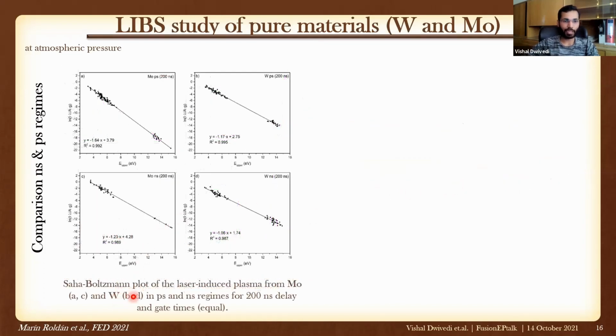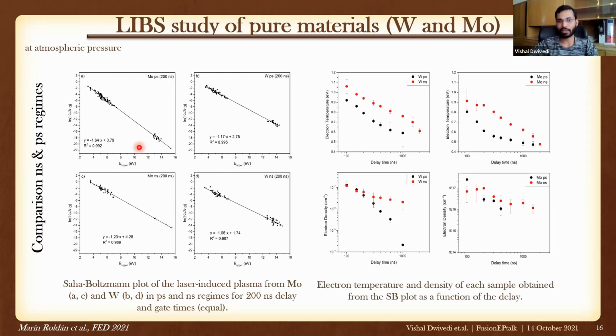Also from the same paper, these are the Saha-Boltzmann plots. From here we can evaluate the plasma temperature. These are for picosecond tungsten, picosecond molybdenum, nanosecond molybdenum, and nanosecond tungsten. If we are in the nanosecond regime, the delay is quite short, 200 nanoseconds here. So we see very few ionic lines, mostly neutral lines. And we can observe similar things in other figures also.